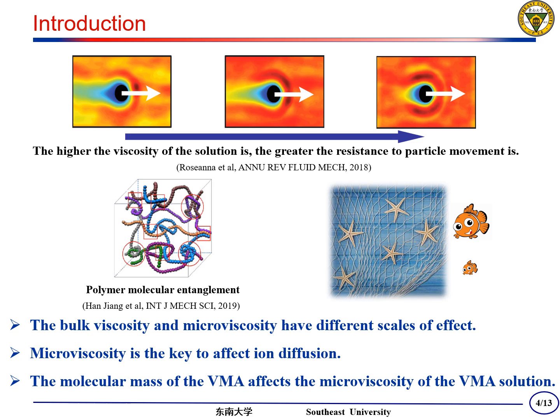Microviscosity is usually smaller than the bulk viscosity and reflects the viscosity behavior of a medium on a smaller length scale. The size of chloride ions is much smaller than that of polymer, so microviscosity is the key to affect ion diffusion. VMAs with small molecular mass have lower efficiency in increasing viscosity. However, when the molecular mass becomes too large, VMAs can no longer increase the microviscosity or even decrease it, while the bulk viscosity remains unchanged.